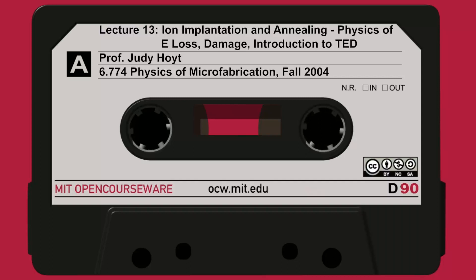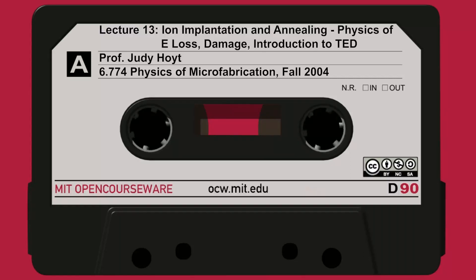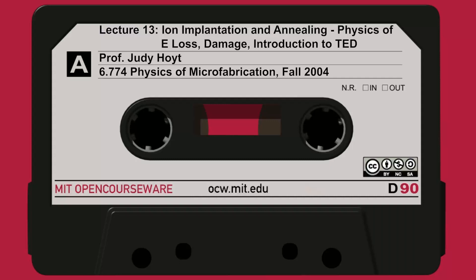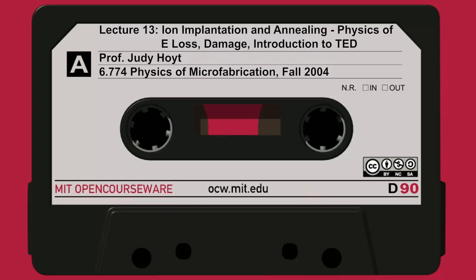There's no melting going on — in a layer-by-layer method, the atoms in each layer take the template from the substrate and rearrange themselves back into single crystal form. This amorphous layer progresses from depth towards the surface in a linear fashion — it's epitaxial growth. We call it solid phase epi as opposed to vapor phase epi. As time goes on, it regrows. When you're done — maybe after half an hour — the entire amorphous region will have regrown and be all single crystal. However, you'll be left with a band of residual damage called end-of-range (EOR) damage, which are defects just below the original amorphous-crystalline interface. Those are pretty hard to get out and generally don't ever go away.